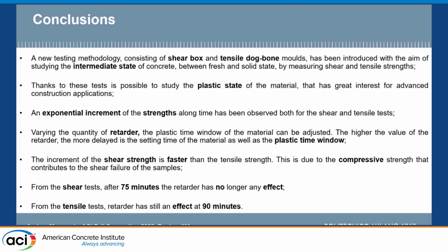So, concluding, a new testing methodology consisting of shear box and tensile dog bone molds has been introduced with the aim of studying the intermediate state of concrete between fresh and solid state by measuring shear and tensile strengths. Thanks to this test, it's possible to study the plastic state of the material. An exponential increment of the strength with time has been observed both for the shear and the tensile tests. Varying the quantity of the retarder, of course, varies the plastic time window of interest.